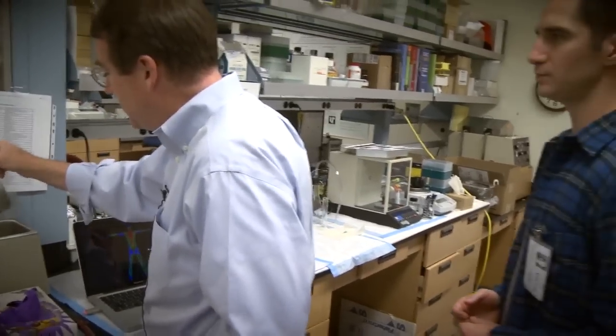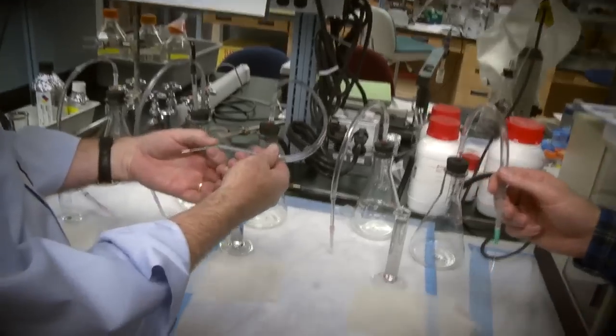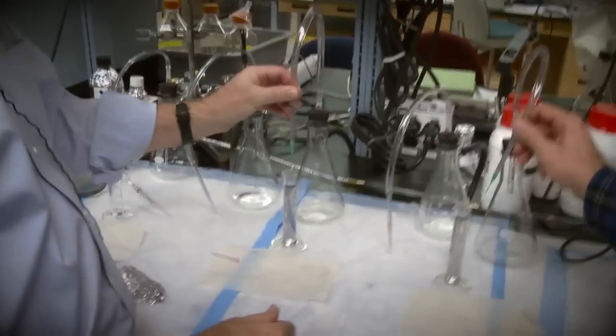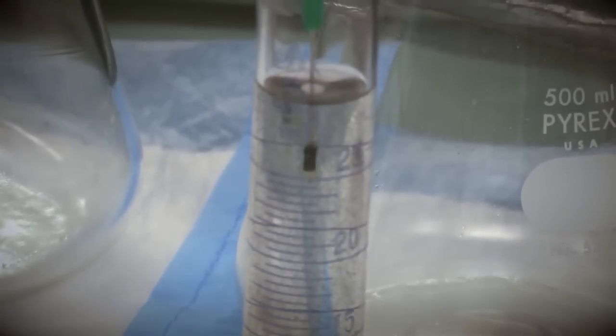We have a solution of carbon nanotubes ready to go here — just in a simple solvent, in this case acetone. I'll attach the needle. At the tip is a porous plastic which serves as a mold to actually make the capsule. And then we just plunge it into the solution. You'll notice that instantly the carbon nanotubes start to deposit on the outside of the mold.